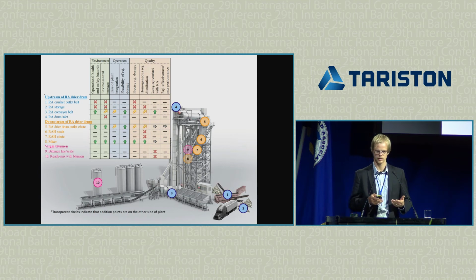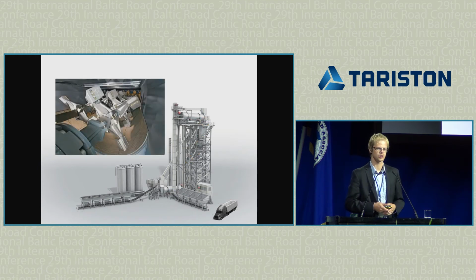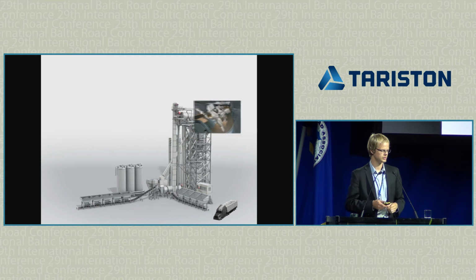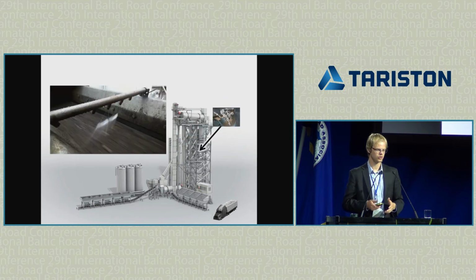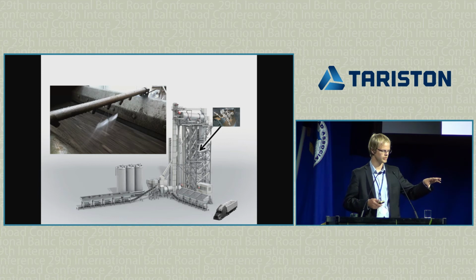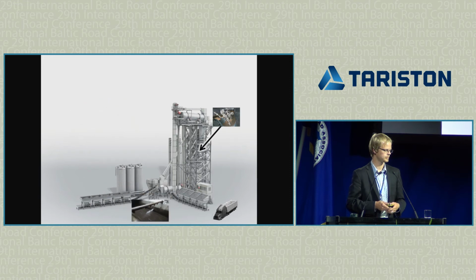So, at the end, based on this theoretical calculation, we saw that there are 3 different options. 2 of them are quite similar, so we decided to focus on 2 of them, and we went ahead in an asphalt plant and tried these 2 different options of rejuvenator addition. One of them is adding the rejuvenator after the reclaimed asphalt has been heated in the mixer, that's somewhere here. And the other option is to add the rejuvenator to the cold asphalt right after it's leaving the cold storage bins on the belt. So here we are able to control the dosage based on the volume of the material. Okay, so that's here.